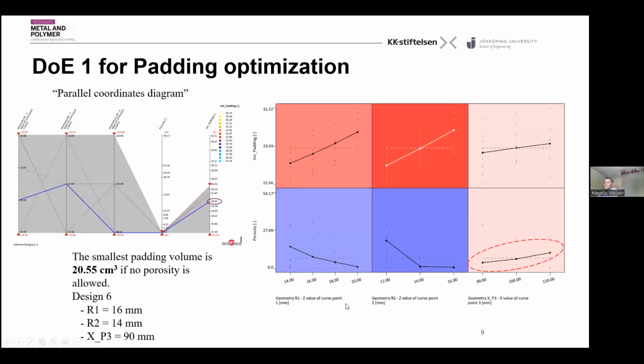And if you do that, you get out, I don't remember how many optimizations I ran, but I run now from 14 to 20 millimeter for radius 1, 12 to 16 for radius 2, and the position from 90 to 110. And then you can analyze it in what we call the parallel coordinates diagram. Then if I just drag these points, and say I only accept the solutions where I don't have any porosity, you can directly see the combination of parameters which yields some good results.